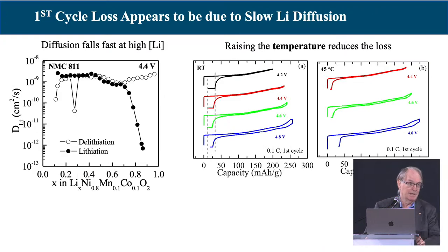So what we did was measure the diffusion coefficient, the black circles there, of lithium going into the lattice. And I think you can see the lithium diffusion coefficient drops by 3 orders of magnitude when you get more than, say, 70% lithium into the material. This is related to the diffusion mechanism. And if this was a normal classroom, it would have empty seats right in the middle of each row. So if an extra person wanted to come in, then everybody has to move. Similarly here, in the lithium case, you need two empty seats for lithium to move, so all the lithiums have to move. So the fewer of these vacancies, the slower the lithium diffusion coefficient. So that's what's slowing it down.